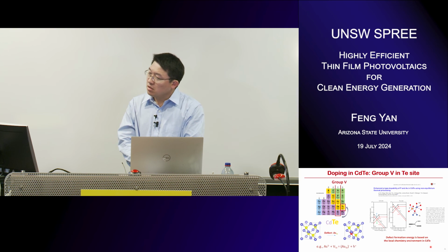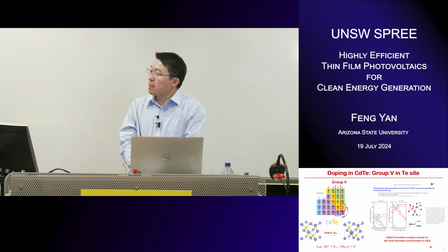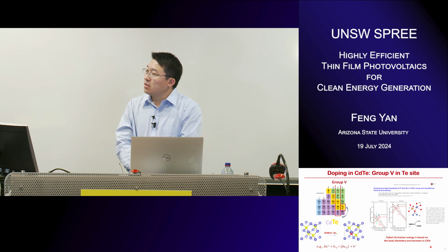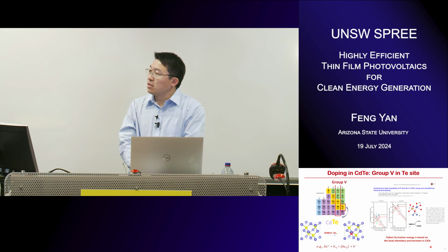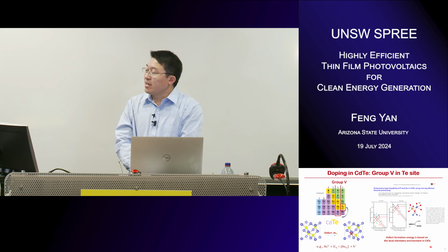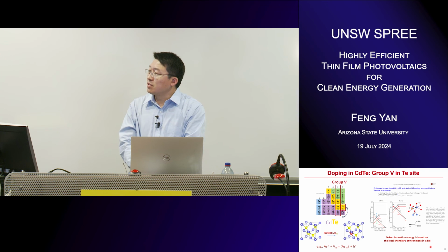So my further follow-up question, I'm not quite sure whether that has been done, but I believe it has already been done. After the cadmium chloride treatment, did we see the CL intensity or even the lifetime increase in the grain interior? Because you talk about the flux, one major role is also the structural crystalline defects, right? So if you already decrease the crystalline defects, you should also see a lifetime increase in the grain interior.